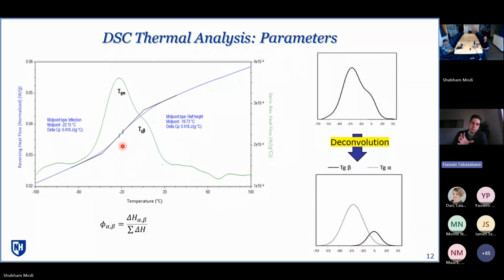And this is important. It's coming from the polymer industry, where polymer compatibilities are assessed by whether we have a combined glass transition or a single transition. The more miscible those polymers are, the more of a single event you see. We're using that same method here to scrutinize the glass transition behavior of bitumen and see what the quality of that curve is. Do we have a single clean glass transition, or do we see a secondary transition occurring? And with aging and RAP, does that further degrade or devolve? So that is the background for why this is being used as part of this compatibility analysis, and why the relative ratios of alpha to beta are of importance to us.